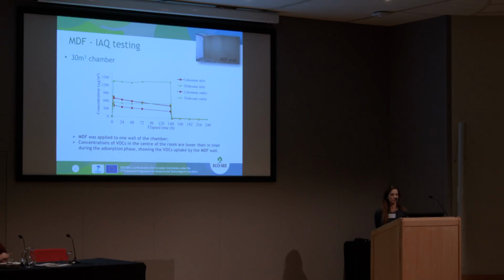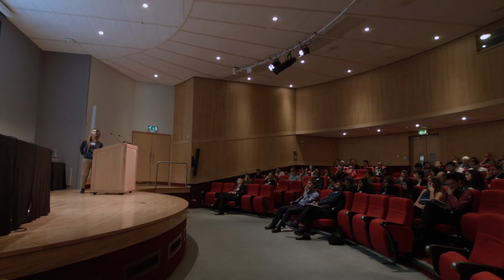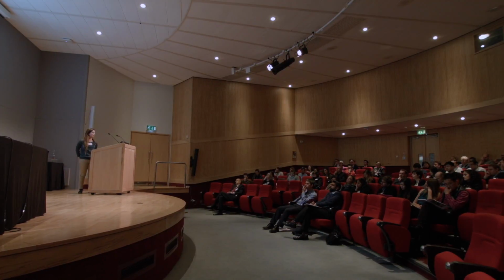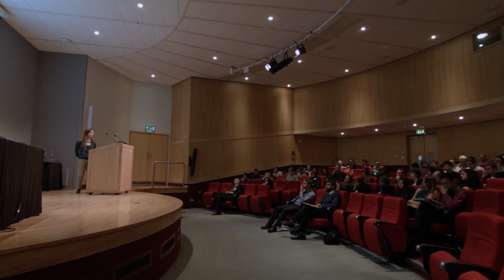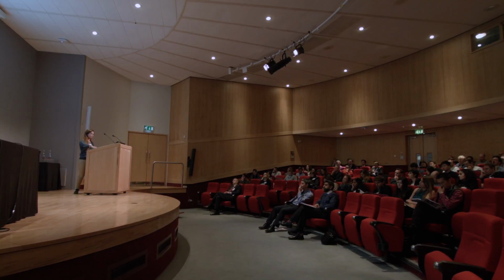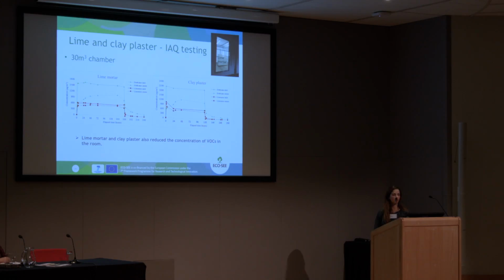Then we did some tests in the big chamber where we covered one wall with MDF, and we observed the reduction of limonene and dodecane. The same for lime and clay plasters, which improved indoor air quality inside of the chamber.